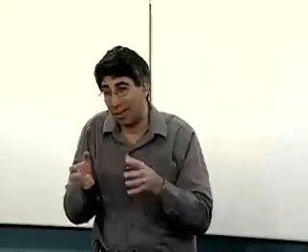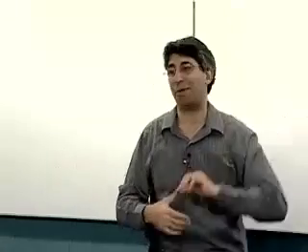On the other hand, a cation that's leaving later on, maybe after the lattice has shrunk somewhat, sees a different effective viscosity for that lattice. It has more trouble getting out, a different diffusion coefficient, and so I expect my diffusion coefficient to reduce with time. Now, again, the particular functional form I have here doesn't mean a thing. It just fits the data. But that would account for everything, that the lattice has to accommodate the diffusion, the cation that's coming in and going out. And I have this expansion and contraction.